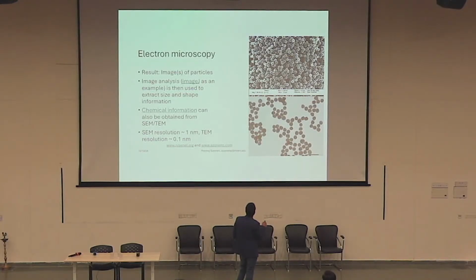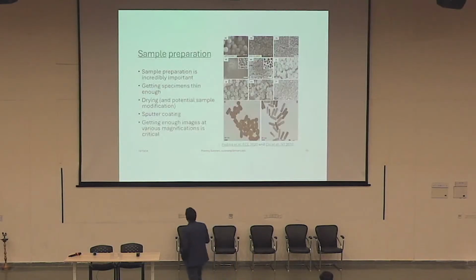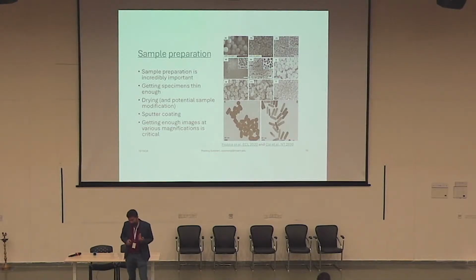And just so you know, this is about 70, 80 nanometers or something, and this is about 10 nanometers, 15 nanometers or something like that. Sample preparation, incredibly important. Guess what? Your samples can't be wet. The vast majority of biological specimens tend to be wet, right? So you have to have a way of tackling water. You have to coat these samples if they are non-conductive. For TEM, you have to make these specimens incredibly thin, right?